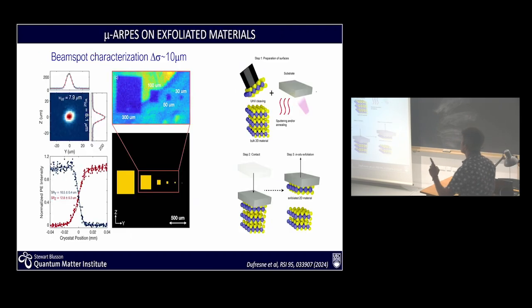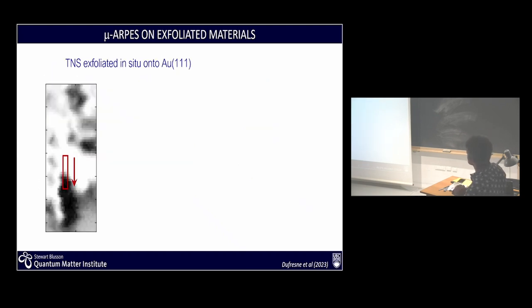And in the last 2 minutes, I'd like to say that we have then pushed the system to see if we can work on the exfoliated version of this system. We have developed a micro ARPES system where we can go down to 10 microns and then exfoliate the materials in situ. So now I'm going to show you work that was done with a 10 micron spot on a flake of the same material done in situ. And here is what you see.